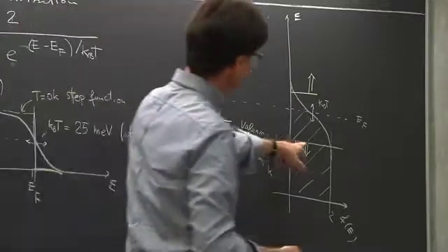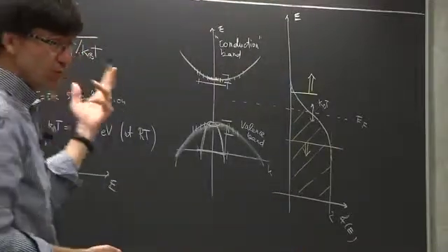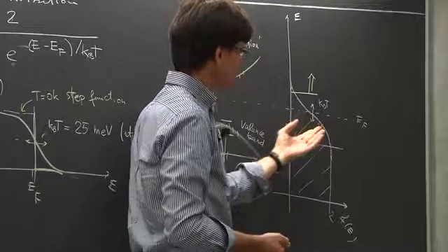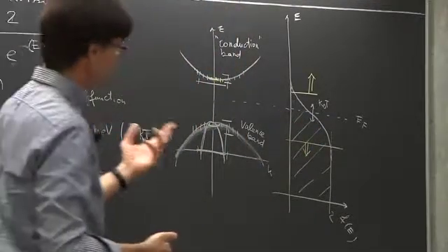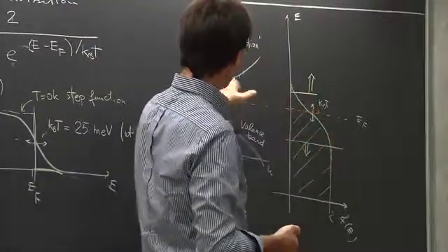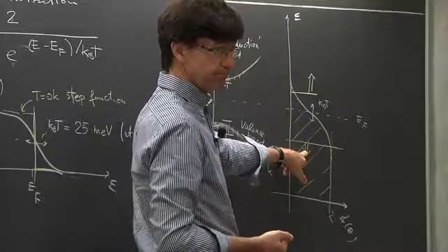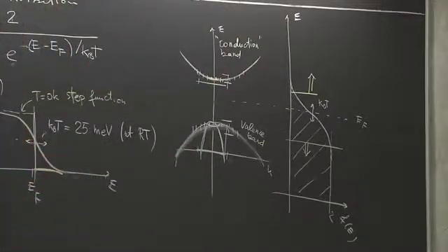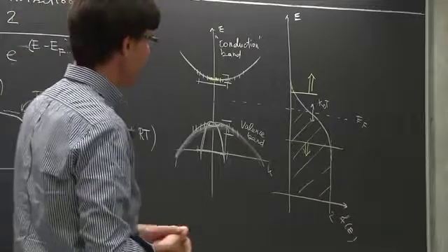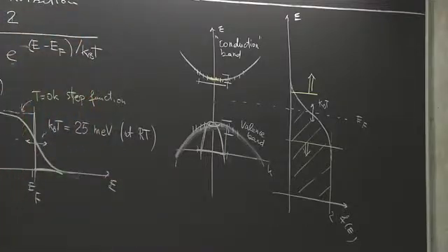So when I do this counting, I don't have to look just at the Fermi-Dirac distribution. I have to consider that this Fermi-Dirac distribution counts the number of electrons per state. But I also have to consider that in this particular case there are more states available here than here. So actually the position of the Fermi level is a subtle concept. It will be close to the middle of the gap, but not necessarily at exactly halfway between the conduction band and the valence band.